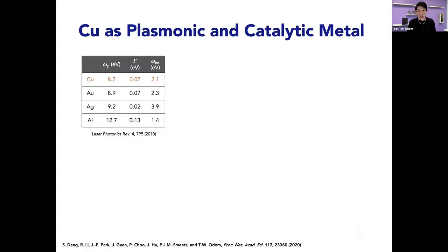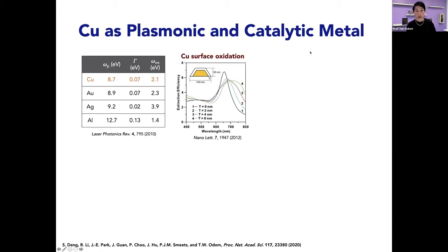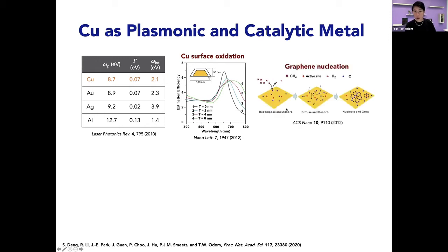So then we are trying to expand the toolkit based on materials. And then we are also interested in multiple functions. And so we focused on copper because copper is a really nice plasmonic material. It can also be directly integrated with electronic devices. And if we look at the Drude model parameters, they're very similar to gold. But the other advantage of copper is that it can function as a catalytic material. And in terms of this, it's very good for nucleating the growth of graphene.